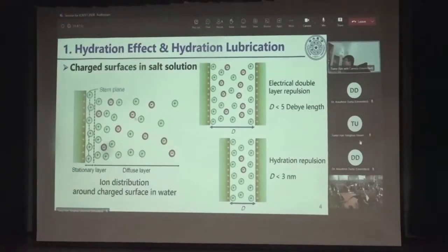When two surfaces approach each other to a distance less than 5 Debye lengths, where the Debye length is used to describe the length of the diffusion layer, we can find a repulsion force, called the electric double layer repulsion. If the distance decreases to less than 3 nanometer, another strong repulsion can be found, called the hydration repulsion or the hydration force.